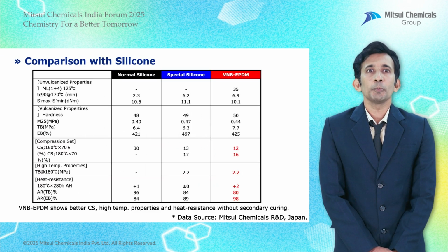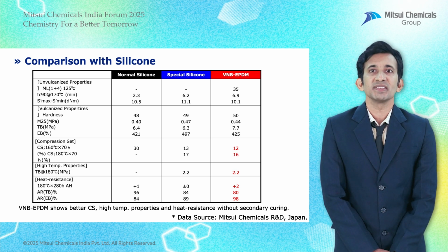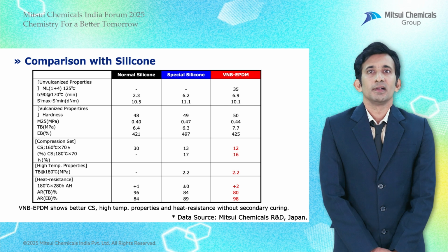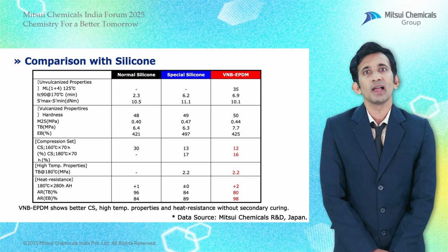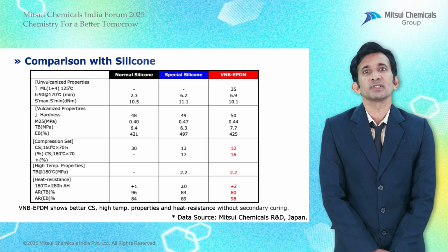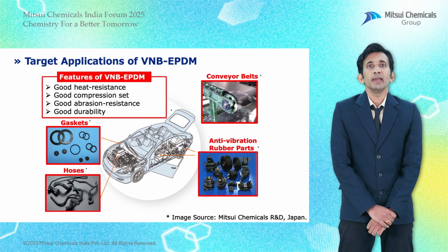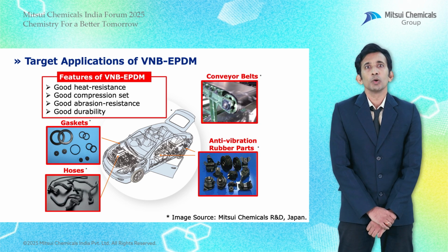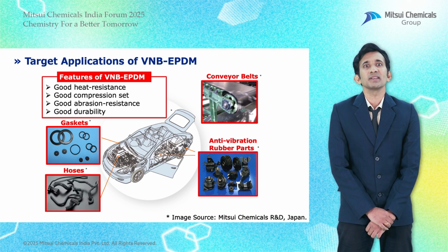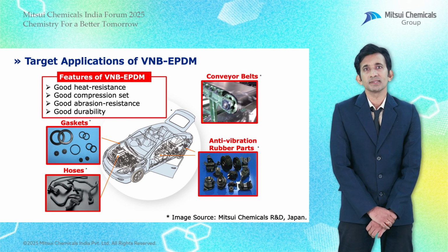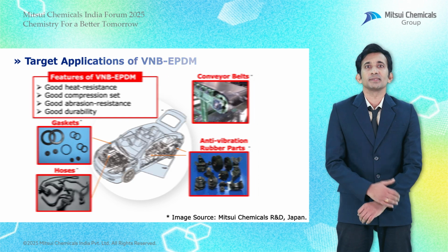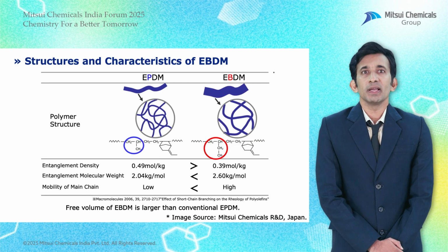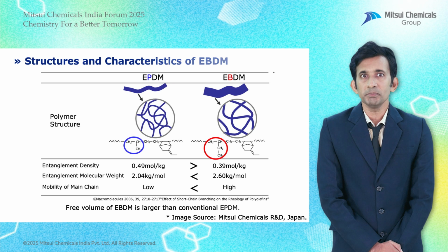VNB EPDM outperforms conventional EPDM and even silicone in compression set and heat aging tests. VNB EPDM shows better compression set, high temperature properties, and heat resistance without secondary curing. With ultra high heat resistance, good compression set, good durability, and high abrasion resistance, applications include hoses, anti-vibration parts, gaskets, and conveyor belts.